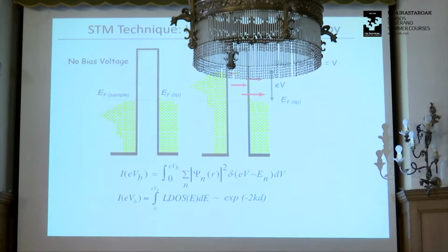And this is a quick slide to get a sort of intuitive feel for what the STM measures. So think about what you have. You have this tip, which is a filled Fermi sea. That's what this is showing here. And you have the sample here. And when you bring these two together, initially the Fermi levels of the tip and the sample will line up, right? Now let's say you apply a potential difference between the two. You can raise, let's say, the sample Fermi energy with respect to the tip's. And as soon as you do that, electrons can tunnel from the filled states of the sample to the empty states of the tip. And that's the tunnel current that we measure.